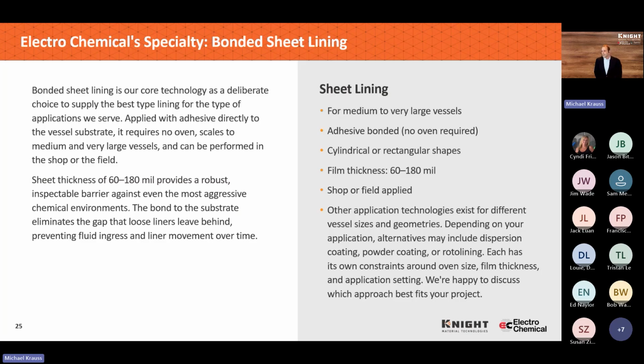Typical sheet thicknesses range from 60 to 180 mils. Most of our linings are between 90 and 120 mils. It tends to provide a really robust thickness that gives some protection against permeation, some against mechanical damage. As you get thicker, the sheets become more challenging to bend and form, so workability becomes more difficult, and the sheet lining material is expensive, so it tends to add costs. So we've done thicker materials, but the bulk of what we do and what we see in industry is between 90 and 120 mils.